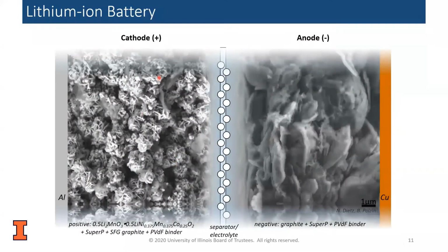This is what it looks like in the microstructure. So besides the active oxide, there will be some Super P, which is a type of carbon black, and SFG, which is synthetic flake graphite. And this actually provides an electrical network that allows the electrons to be transferred between the current collector and the active oxide. And then to hold everything together is a binder of polyvinylidene difluoride.